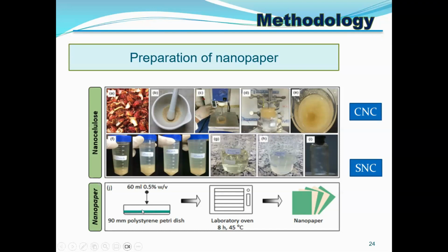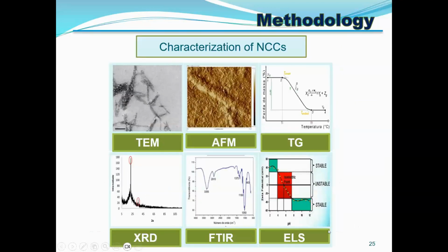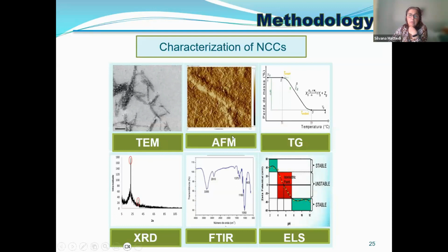And then we used a casting procedure to obtain the nanopaper directly. So it's pure cellulose from this. Just evaporate the solvent, and then we have the nanopaper. We characterize all of them with microscopy, atomic force microscopy, thermogravimetry, X-ray diffractometry, Fourier transform infrared, and also with the analysis of the solution with the zeta potential.